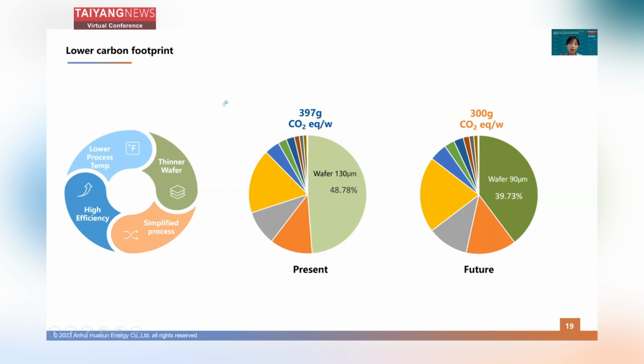So let's look at the carbon footprint value based on the already introduced 130 micrometer wafer thickness. The carbon footprint is already lower than 400 gram. And if we look to the future, after the 90 micrometer wafer thickness is introduced next year, the carbon footprint will be lower, to 300 gram, which is much lower than other cell technologies. This is not only because of the low process temperature and the simplified process for HJT cell manufacturing, but also because the high efficiency plays a big role, further lowering the carbon footprint level per unit.